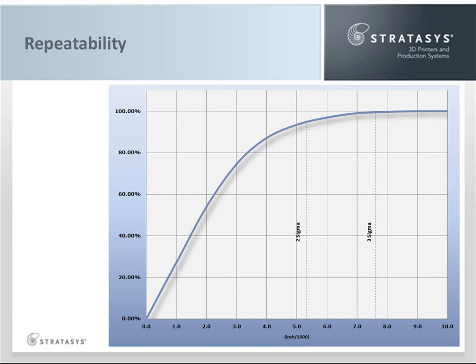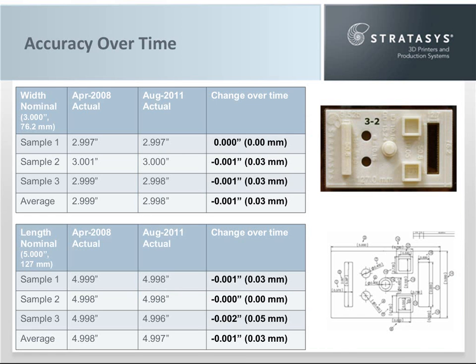I think you'll agree that this is proof that FDM delivers accurate parts with predictable results and very high repeatability. Others may claim it. Stratasys invested in the study to prove that FDM can be your alternative for finished goods manufacturing. And to prove stability over time, we dug out the sample parts from the study, which were just tossed in a box to take a few measurements. The results are shown here, and as you can see, there was very little change over time. The results show that FDM is accurate, predictable, and repeatable.